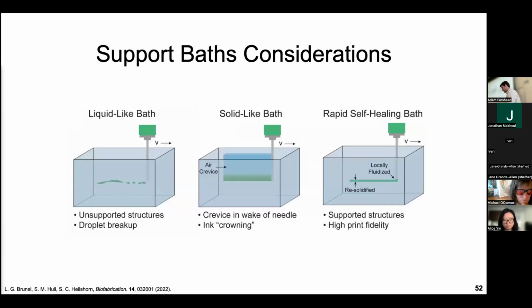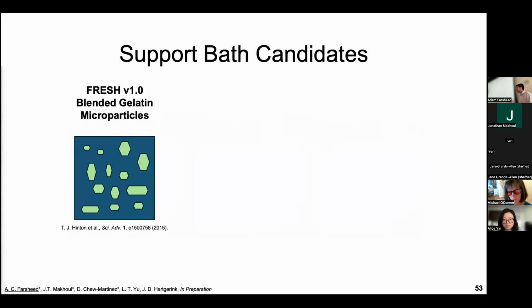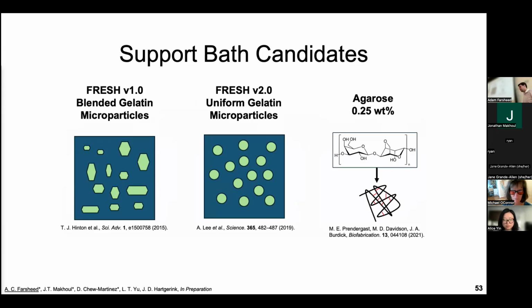And so before I dive deeper into how we did this, the first thing that we need to consider is what are the possibilities that can happen with the support bath? Well, if we have a support bath that's too liquid-like, similar to the solution we were extruding those noodles into, you're going to get your material not forming nice fibers, and you're going to get some breakage. Whereas if your bath is too solid-like, your material is actually going to flow in the wake that's created when that bath is deformed. But if you get the perfect bath that matches your material properties, you're going to be able to create these nice fibers when printing.